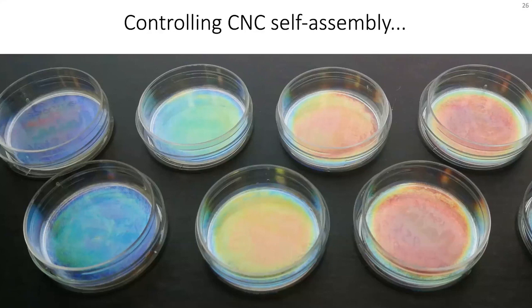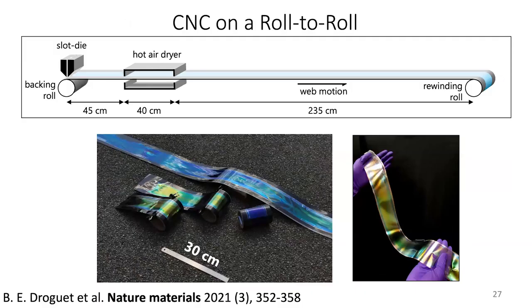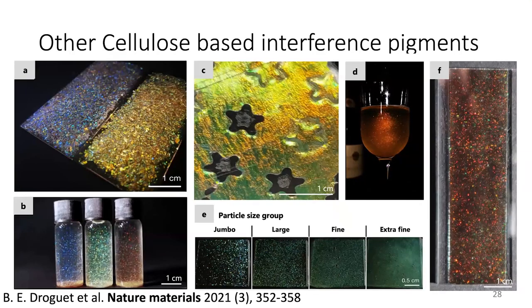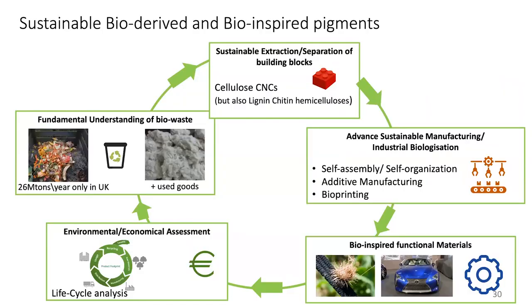Also here we really try to push the technology forward and make material on a large scale. This is an example of a really large film where we are able to control the interaction of the cellulose from the nanoscale to the meter scale to produce laminates that we can then cut and produce pigment out of. So just to conclude, we are really excited because we are able to nicely control the preparation of the cellulose, and we are able to make material using scalable manufacturing techniques, like roll-to-roll, but we also use printing.